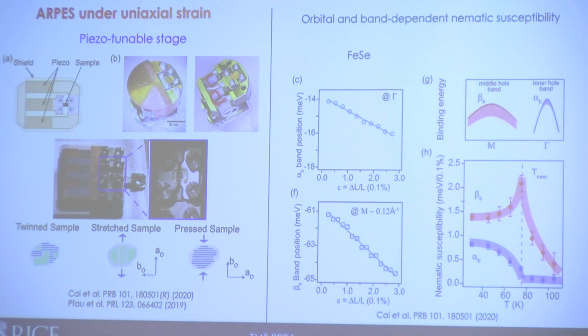The kind of measurement you can do with this kind of tunable uniaxial strain is the nematic susceptibility measurement. So basically, this is nice work by Yan Zhang's group at Peking University. This is really a very nice paper. What they have done is they can measure the amount of band shift in response to the strain for different parts of the momentum space. You can see the linear response, and this one is measured around the gamma point, this one is measured around the M point. You can extract the slope of this linear response, and that slope can be measured as a function of temperature.